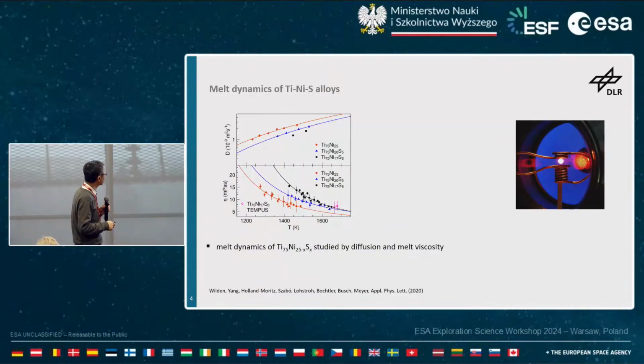This is not part of the composition which we want to do at the space station, but this is an intermediate sulfur concentration alloy where we study the liquid behavior, especially the dynamics of the liquid as a function of sulfur content. This is partially done also here in the electromagnetic levitator, which has the same or a similar version on the space station. I will show you also later on, because we have a parabolic flight facility, how this is done. But Florian will talk more about the facility on the space station. What you see here, what is interesting, is that the viscosity increases with increasing sulfur content, up to the best glass former in this case.